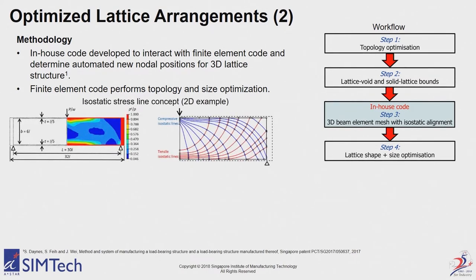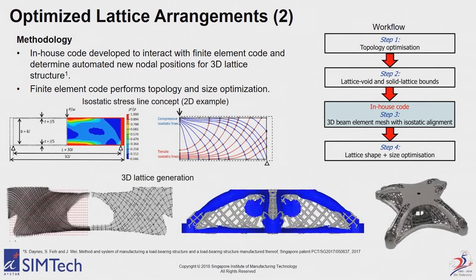The way this works in 2D, as a simple example, is if we have a three-point bending beam, we can see that the stress lines are quite simple in this case. So we could align our beam elements with those stress lines. If we do the same thing in 3D, we have a bit more of a complex algorithm, but basically the algorithm creates the stress lines in 3D and then merges them and puts in the right distance depending on the stress magnitude. And then at the end, we also do a size optimization and a shape optimization.